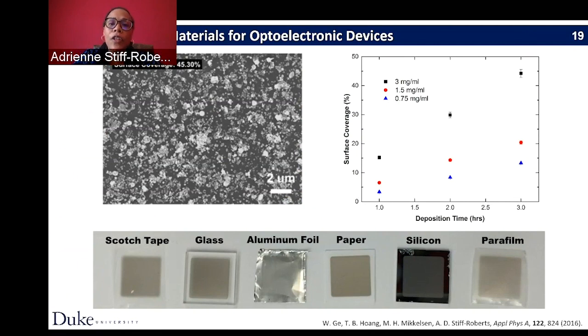These are actually silver nanocubes that have a side of about 80 nanometers, so a relatively large nanoparticle, and this shows that we can control the surface coverage of deposition by MAPLE just by controlling the concentration of the solution or the time that we do the deposition.